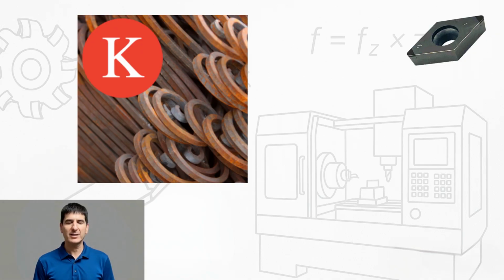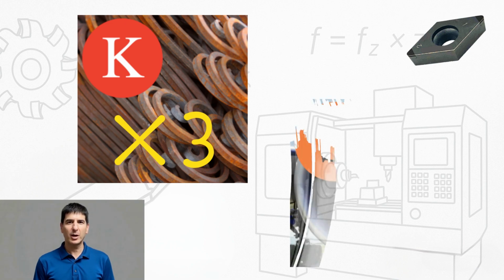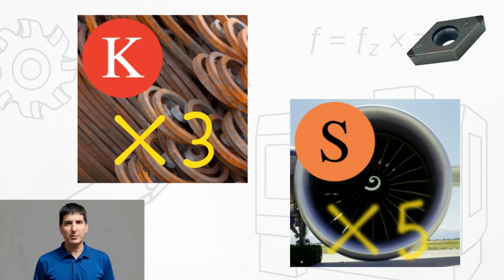On cast iron, CBN can run 3 times faster than coated carbide. We're talking 1500 millimeters per minute, or 5000 SFM. For superalloys like Inconel, you can run 5 times faster. Here, in some cases, the increased productivity can justify the higher cost. But there are more trade-offs. The high price is obvious, but there's also the limitation on depth of cut. You're restricted by the size of the brazed CBN tips. There's also the option of solid CBN inserts for heavier machining, but the cost becomes astronomical.